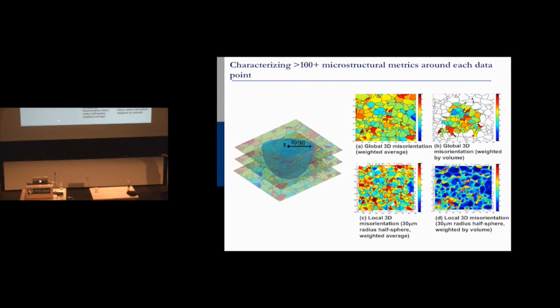So you have this reconstruction. You take a point right here, and you examine a local area, kind of like a half sphere around that point. The radius that you look at is probably going to depend on the strain at that point. We don't know, but we think it will, from some of the work that's coming out of CMU. And something as simple as misorientation: that's how misoriented the grain is with respect to the grain next to it. If two grains are perfectly aligned, there wouldn't be a grain boundary. It can be in 4 different ways. So here's that microstructural field of view.